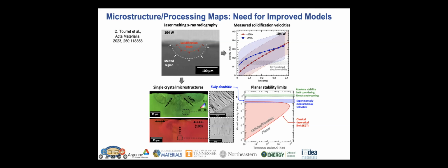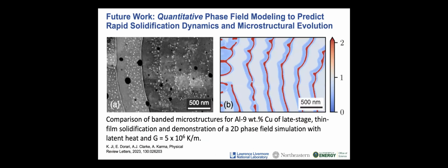So if we look at our fully dendritic microstructure shown here in blue for our maximum velocities experienced, we know that we still have dendrites beyond what's predicted with classical theory. So this suggests there are other things we have to start incorporating into the modeling, things like kinetic effects that are going to be really important moving forward to do predictions for rapid solidification scenarios. And this is some example work that we've been doing with my colleague Alain Karma at Northeastern University, where we're doing a quantitative phase field modeling to predict rapid solidification dynamics and microstructure evolution.